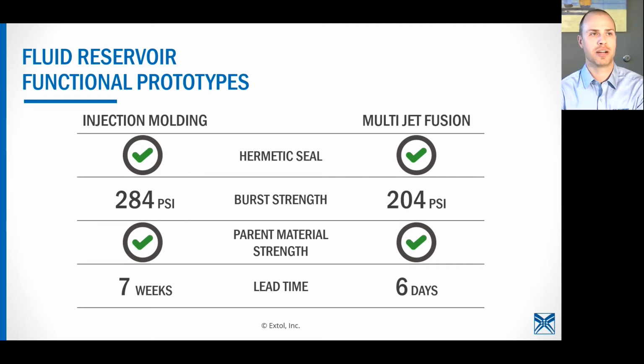Here's a head-to-head comparison for one application we did of injection molded parts versus MJF parts for these fluid reservoirs. You see both achieved a hermetic seal. The burst strength on the injection molded parts was a bit higher, but the MJF parts still met the requirement. Both achieved the parent material strength in that burst test, and the lead time's the kicker, right?